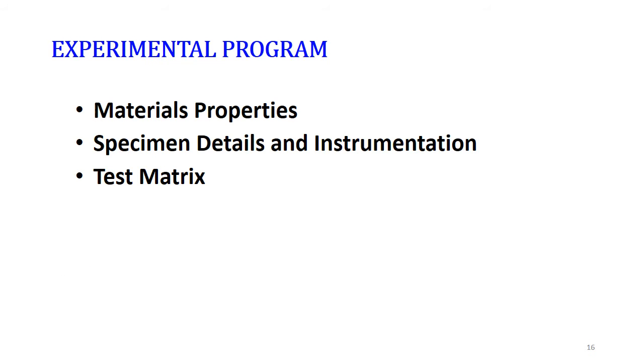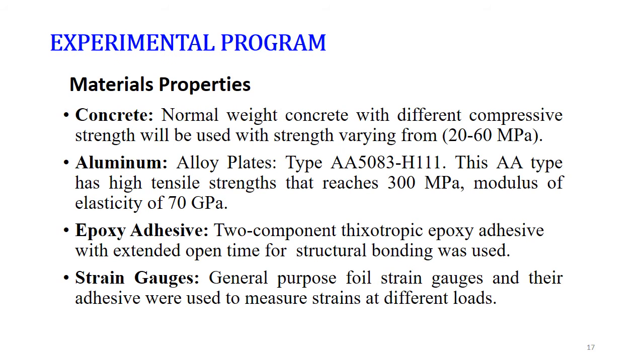The experimental program has material properties, specimen details, and instrumentation, and then the test matrix. I will go a little bit fast on this. We have different materials involved: the concrete, the aluminum alloys, the epoxy adhesive, and the strain gauges used to instrument the specimen and measure the strains. Of particular interest here are the aluminum alloy plates. We use specifically aluminum alloy 5083-H111, which has a tensile strength of around 300 megapascal and a modulus of elasticity of around 70 gigapascal.